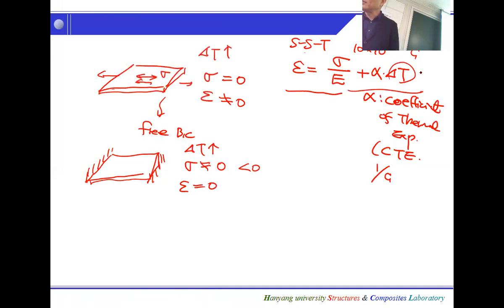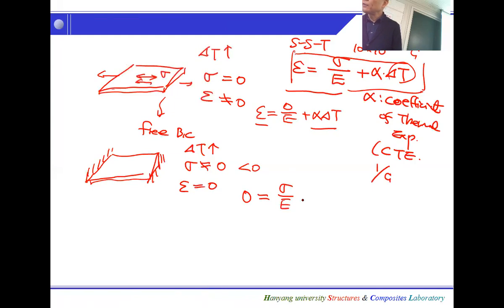So if we look at this stress, strain, temperature relation, in the free case, sigma equals 0, so strain is equal to alpha delta T. As you can see immediately how much expansion we have, depending on how much temperature we increase. Now, the same equation applied to this second case: strain is 0, so 0 equals sigma over E plus alpha delta T. So sigma is minus E alpha delta T. This is the compressive stress that has to develop inside the material to meet zero strain.